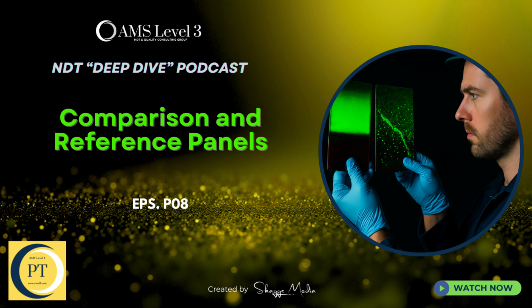Completely subjective, yeah. But I think the lingering thought, the real takeaway that connects all of these, is how incredibly difficult perfect reproducibility is. Think about it. No matter how you make a crack, fatigue, quench, fracture, the very tip, the initiation point, has dimensions that are practically infinitesimal, submicrometer. And those tiny spaces have immense capillary force. So the very thing that makes the crack hard to find, its tightness, also makes it incredibly good at trapping, well, anything. Contamination, old penetrant, cleaning agents.